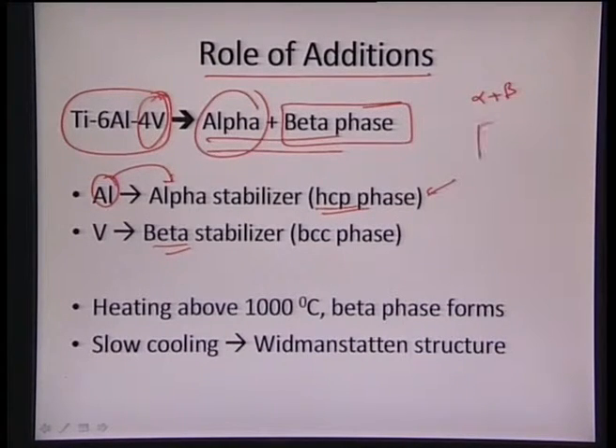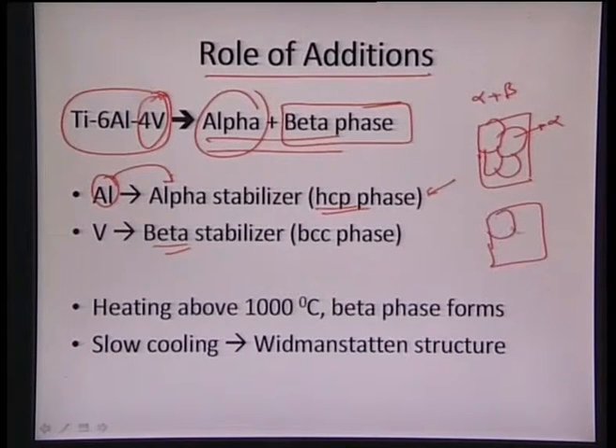So now instead of having a single phase, like in case of titanium, we had only single phase which was nothing but only alpha, and in this case we see that we have a dual microstructure. So we are seeing a kind of a dual microstructure out here, and in this case some certain pockets are only beta. So we can see this alpha plus beta. So we see this is beta and this is again alpha. So we see a dual phase microstructure which basically assists us in terms of achieving even higher strengths and very high fatigue strength once we have a dual phase microstructure.